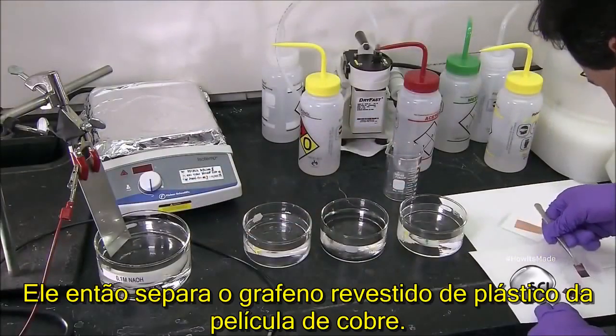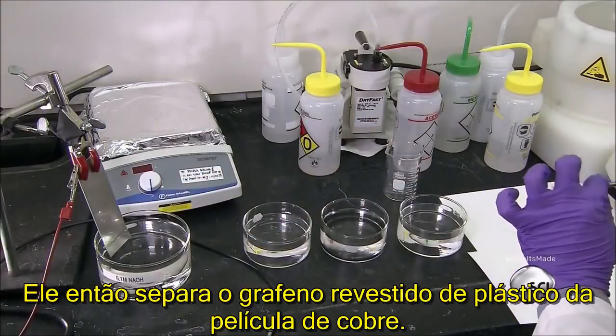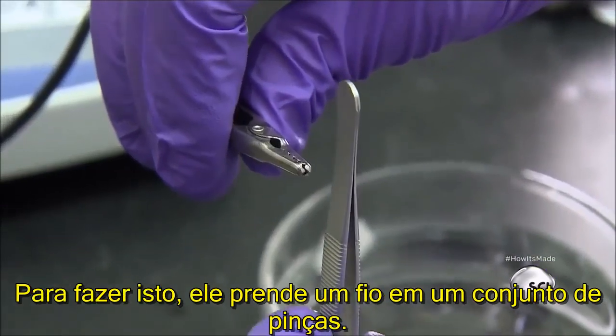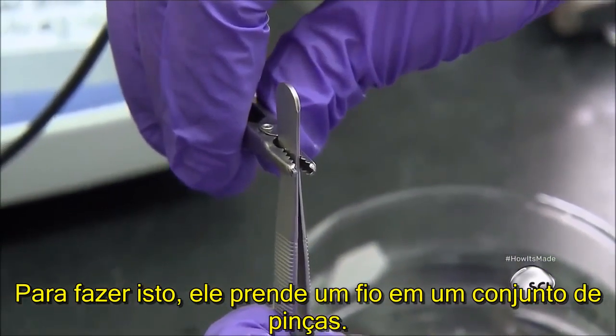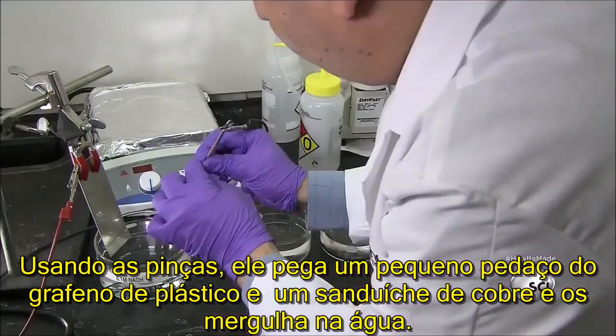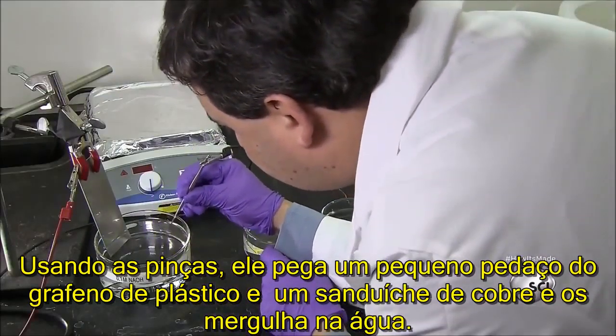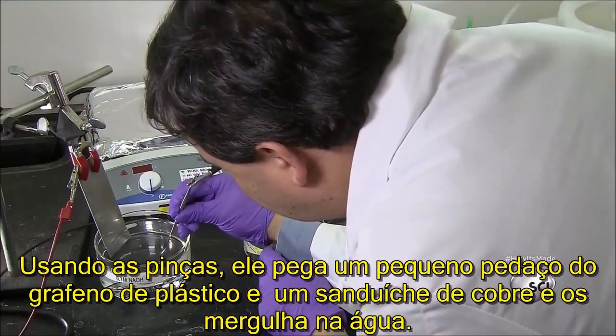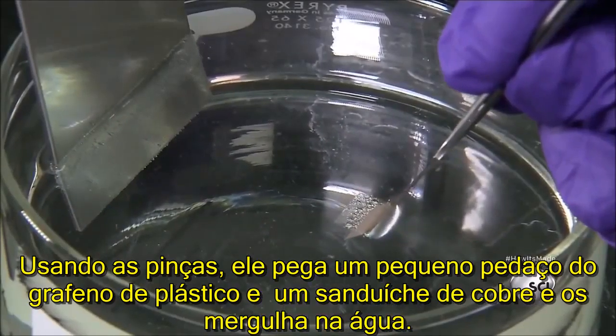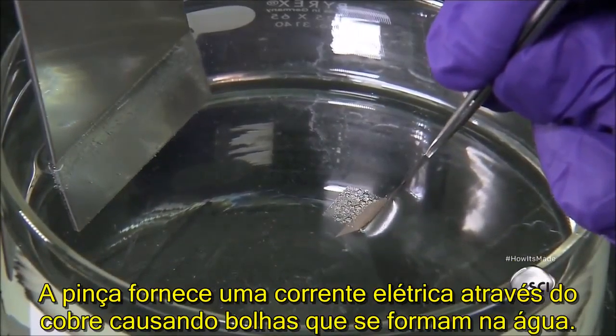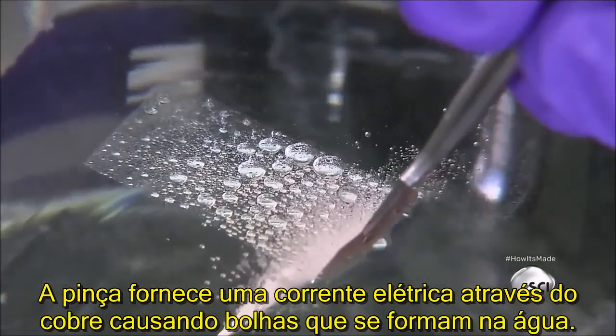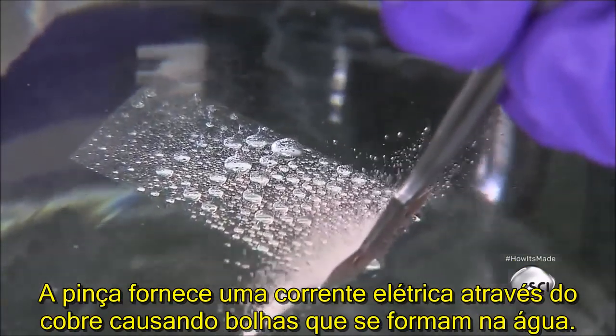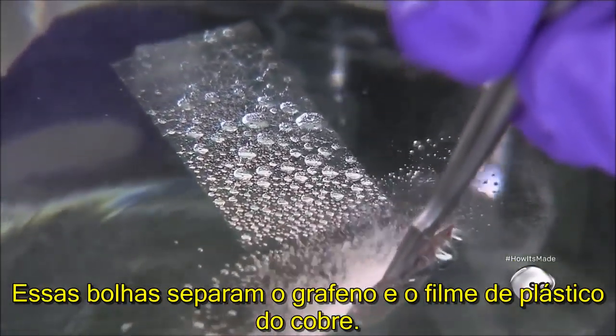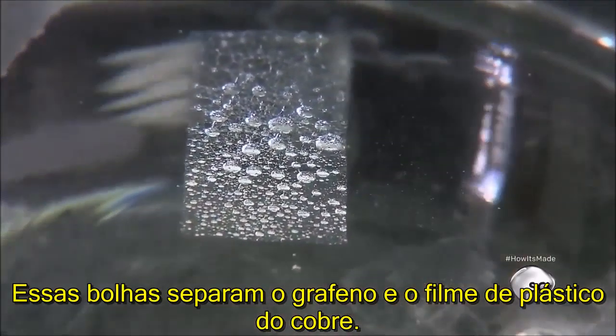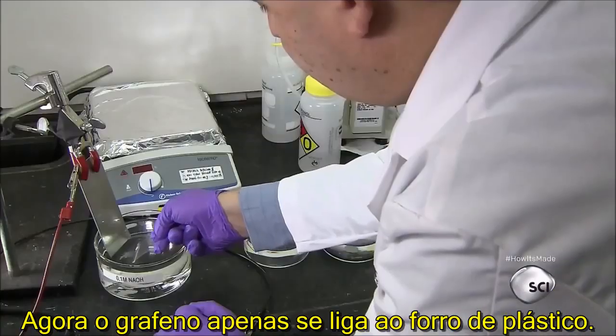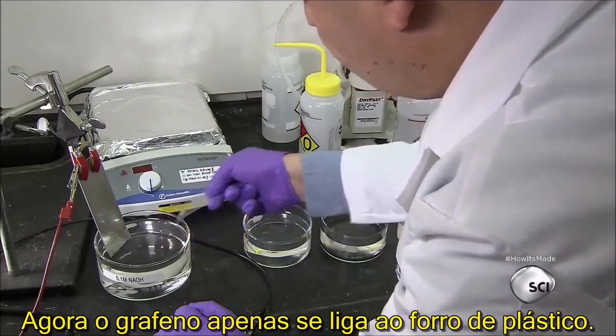He then separates the plastic-coated graphene from the copper foil. To do this, he clips a wire to a set of tweezers. Using the tweezers, he picks up a small piece of the plastic, graphene, and copper sandwich and plunges it in the water. The tweezers apply an electrical charge through the copper, causing bubbles to form in the water. These bubbles lift the graphene and plastic film away from the copper. The graphene now clings only to the plastic backing.